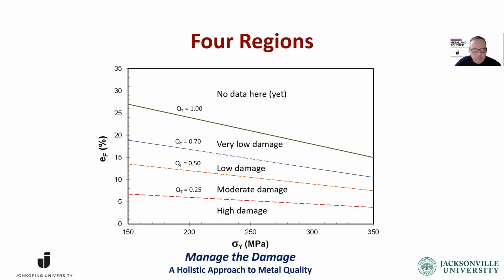So when we look at the yield stress versus elongation area, I divided it into 4. Anything below 0.25 is highly damaged. Between 0.25 and 0.5 is moderate damage. Between 0.5 and 0.7, maybe 0.75, is low damage. And above 0.7 and around 1, that's very good, very low damage. Now, I have not found any data yet above this 1.0. I expect that as we improve the technology, we can get there, and we can get a new equation for the ductility potential. Okay.